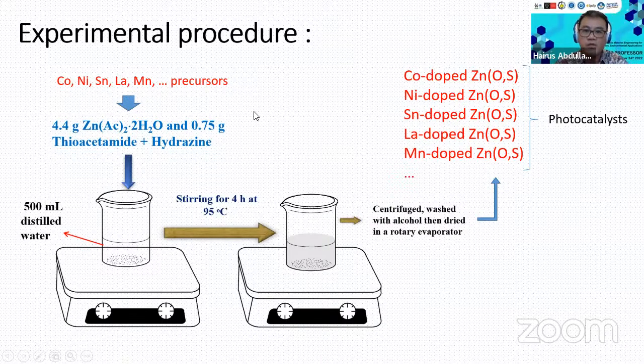And then to improve the performance, we also try to add some precursors like cobalt, nickel, tin, lanthanum, Mn. In a very simple way, we add these precursors during the process. Of course, this process is done separately. Then we can have different doped Zn(O,S) materials, like shown in this figure.